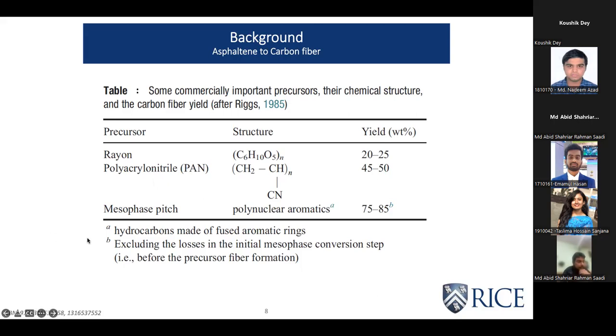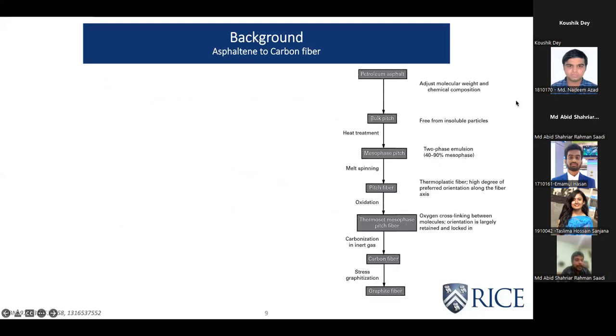But if you look into the mesophase pitch, and asphaltene as a precursor falls under this mesophase pitch category, it has a very high yield of 75 to 85%, almost double what we have for PAN-based precursors. So because of this high yield, we are interested in converting these asphaltenes into carbon fiber. And here, this is a flow diagram that gives a very basic picture of the steps involved in producing carbon fibers from this petroleum asphalt.